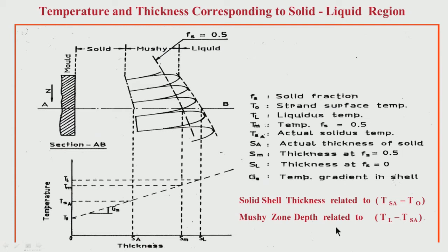One is the last solidification which is taking place, the last area of the solid is definitely more rich in all alloying elements. It is a question of relatively how low is the K value and how low is the diffusivity in solid. If both these two are very low, the segregation will increase. Segregation increases means the particular area which is solidified at the last is more rich.